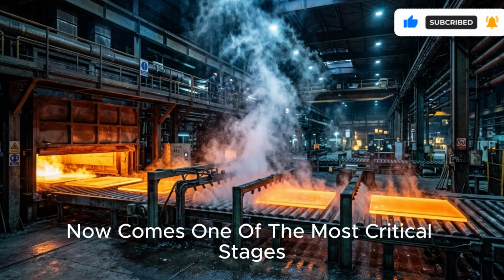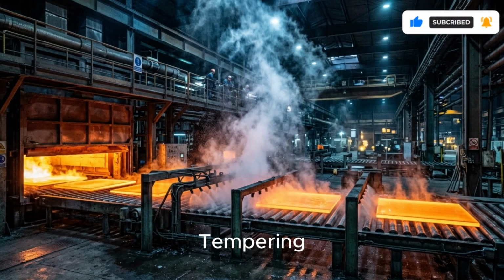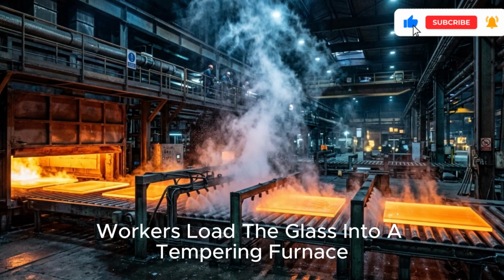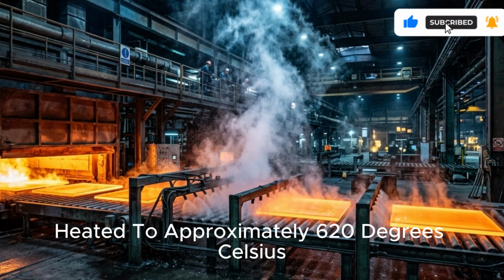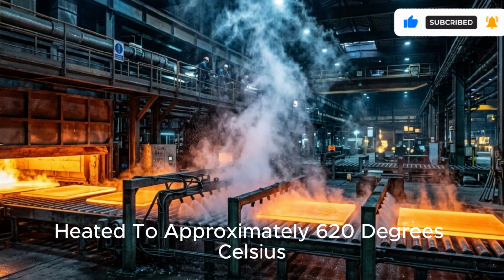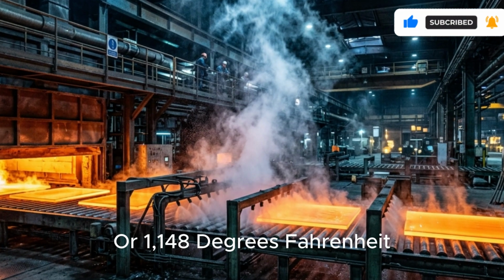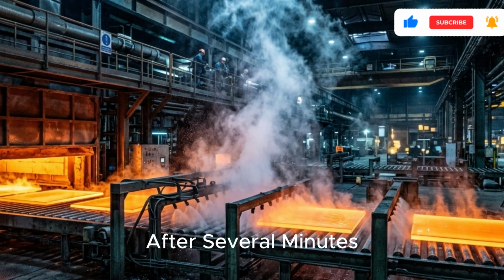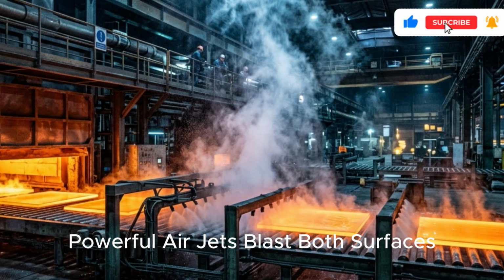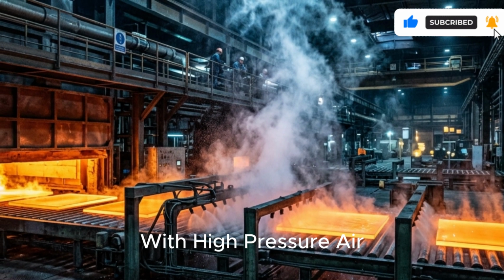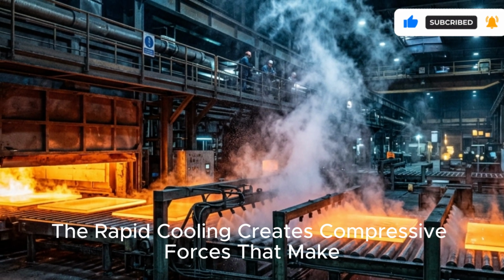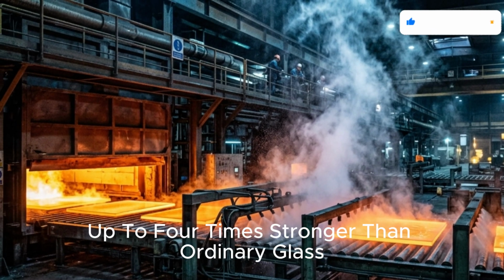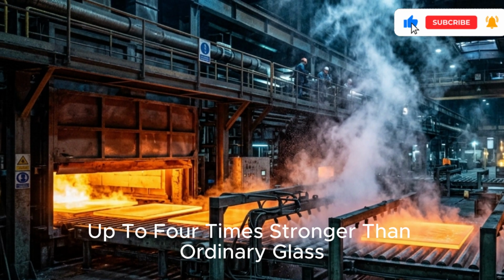Now comes one of the most critical stages: tempering. Workers load the glass into a tempering furnace heated to approximately 620 degrees Celsius, or 1,148 degrees Fahrenheit. After several minutes, powerful air jets blast both surfaces with high-pressure air. The rapid cooling creates compressive forces that make the glass up to 4 times stronger than ordinary glass.